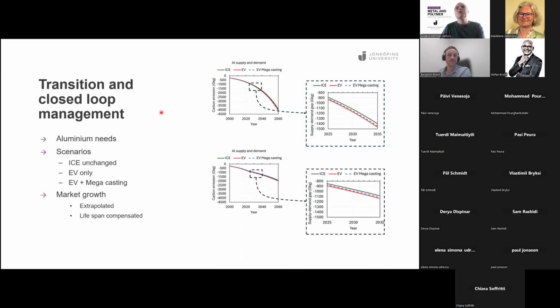If we now look at the growth with lifespan compensated demand, you can see that there's a little bit of a knee point here at 2022 when we start to do that projection. So we see that it's also growing, and the scenario is roughly the same. It's just that the absolute numbers are changing because the volume of the market is different. Now, this is no surprise. We always need to add aluminium to this. So either you buy secondary aluminium and you add that as a dilution, or you buy virgin aluminium and you add that, depending on how the actual component will be produced. But there will always be a gap and a need for new aluminium entering the system anyway. It needs to be taken from other sources than the automotive scrap. That is what I'm saying here.